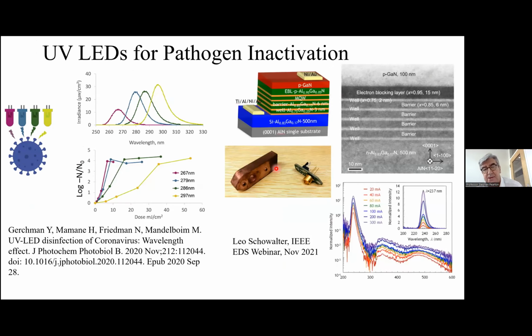Now, we're all too familiar also with using UV LEDs for disinfection and killing things like the coronavirus. And there, instead of using an InGaN quantum well, you're going to use an AlGaN quantum well with very high aluminum composition. And the higher you go, the shorter the wavelength of emission, and the shorter the time it takes to kill off things like coronavirus. So these LEDs are widely used now to disinfect public spaces. You can turn them on and quickly kill any viruses that might be there. So you're talking about emissions in the 225, 230 to 250 nanometer region.